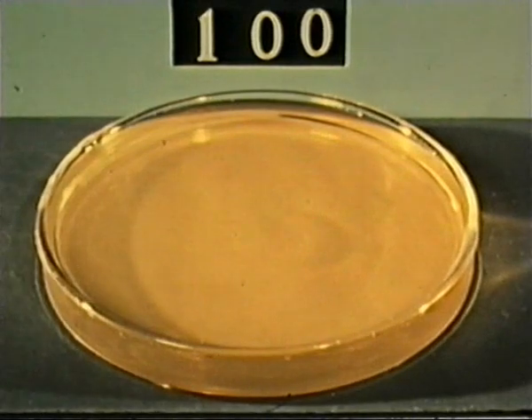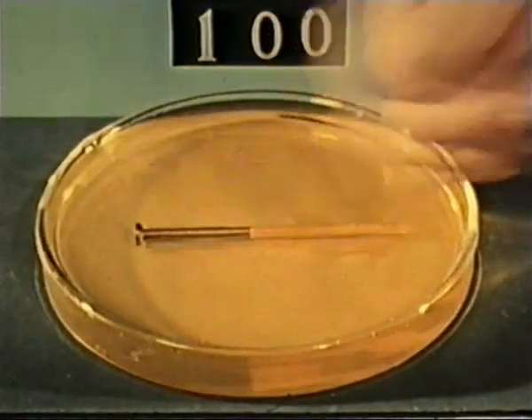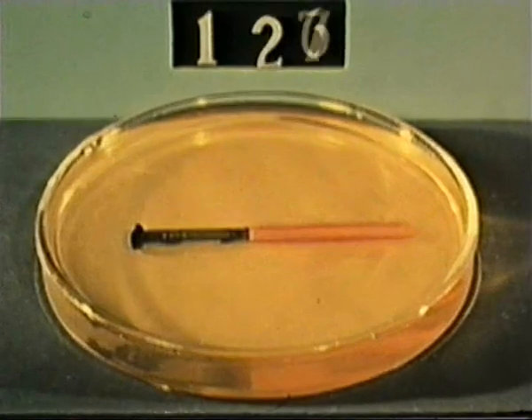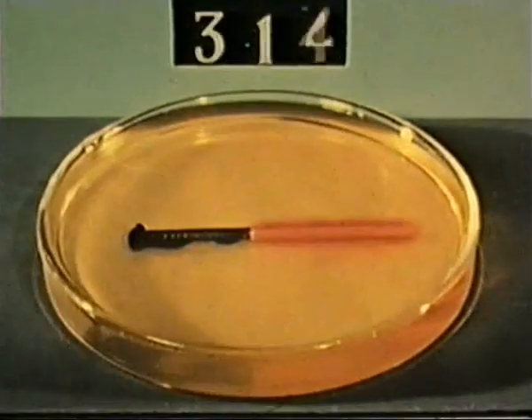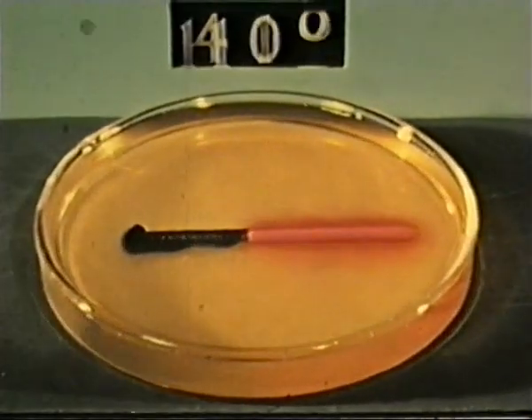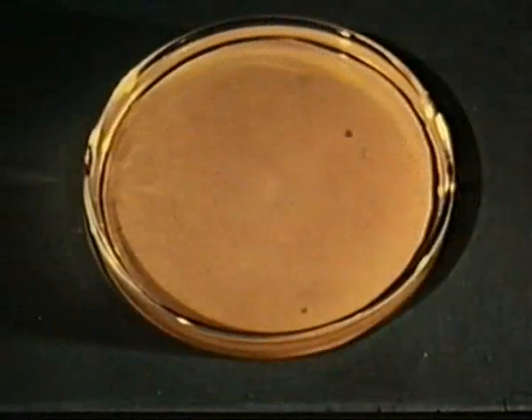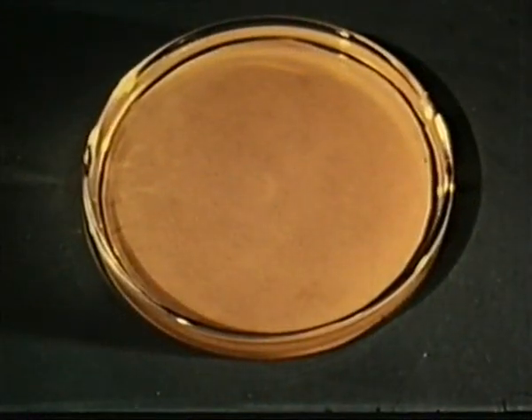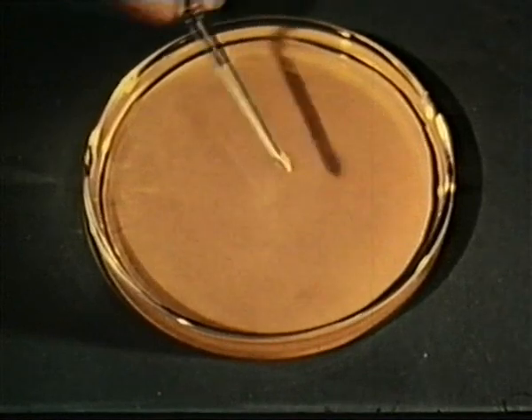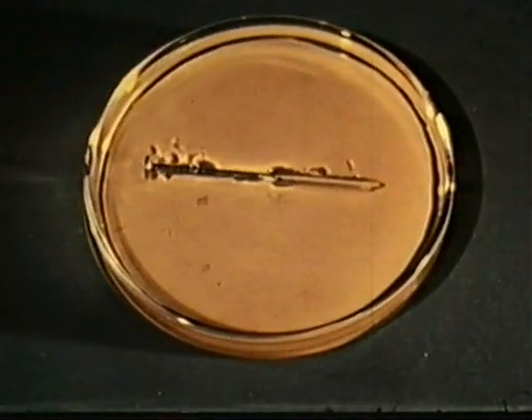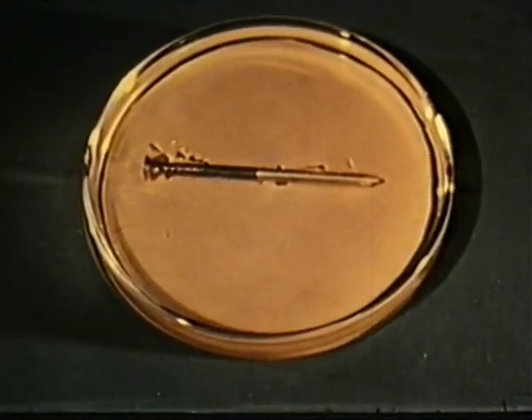By speeding up the action, we see that the colors become more intense with time, showing that iron continues to corrode and at the same time there is an increasing concentration of hydroxyl ions. If we combine iron with a more active metal like zinc, we have a couple where now the iron acts as a cathode and the zinc as anode.